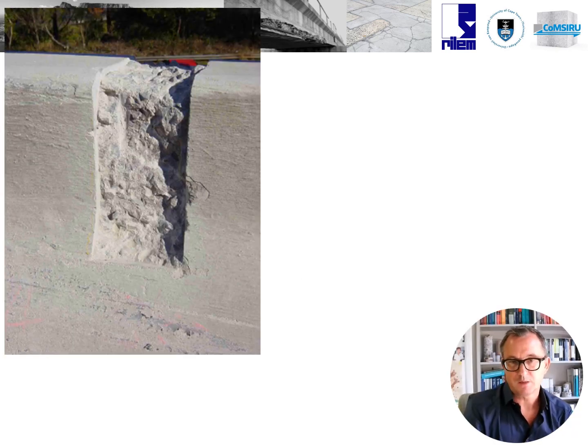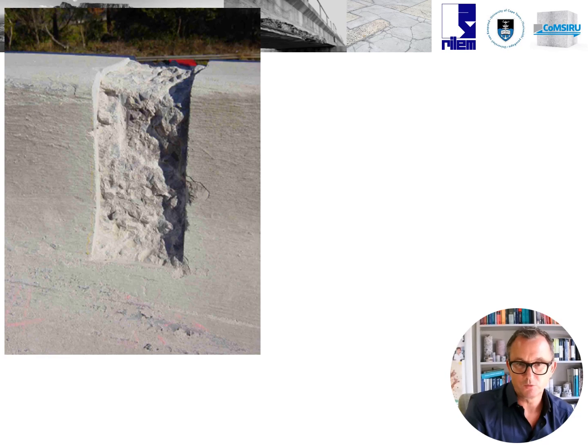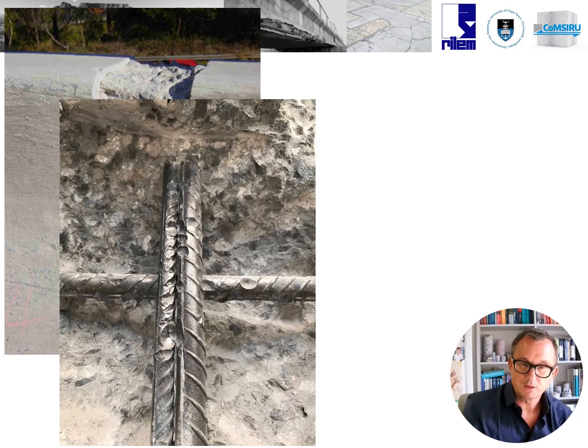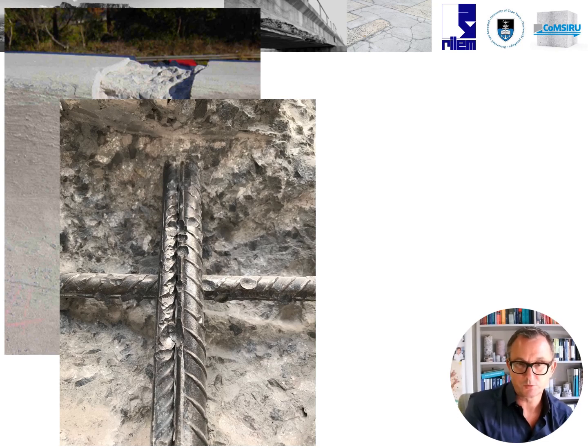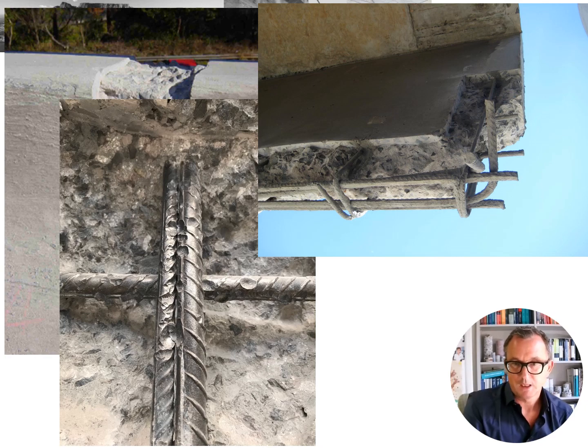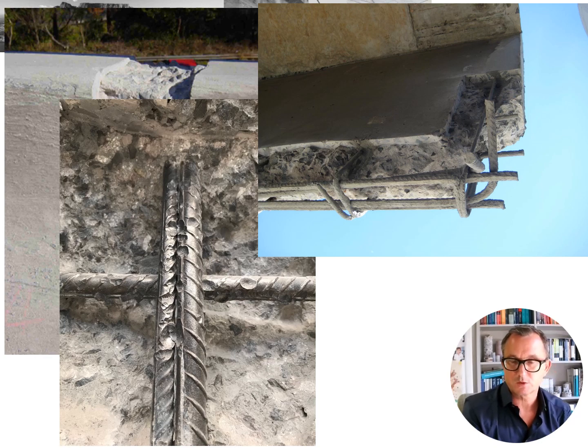Patches should have straight corners which are neatly cut, after which the concrete can be removed. If you expose the steel, you need to clean all the rust off the steel and make sure the steel is free of any corrosion products. Here is an example of how it should look: the concrete has been removed, the corners have been cut straight, the steel has been cleaned, and subsequently the steel was coated with a protective coating to minimize the risk of future corrosion.